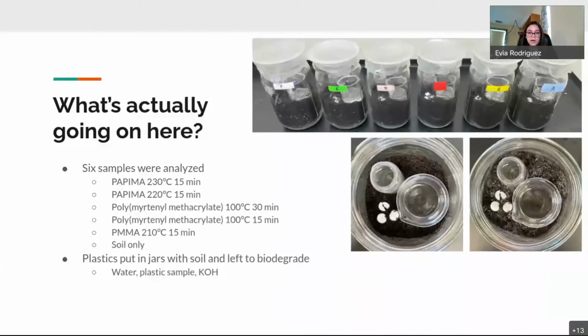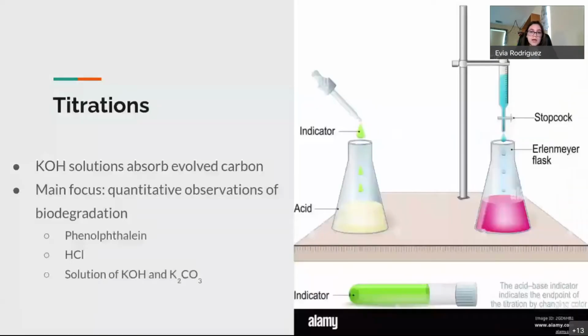Each jar, as you can see on the right, has water, a certain amount of one plastic sample, and a solution of potassium hydroxide. The potassium hydroxide is important, and it's the main component of how I'm measuring the biodegradation, because I'm using a titration to identify how much carbon evolved from the plastics. During the biodegradation process, essentially what happens is microbes will eat the plastic, and as a byproduct, they'll release carbon dioxide. And the carbon dioxide contains carbon that came directly from the plastic.